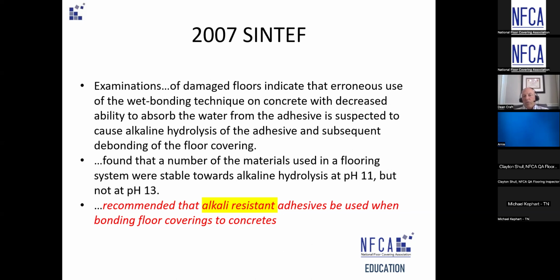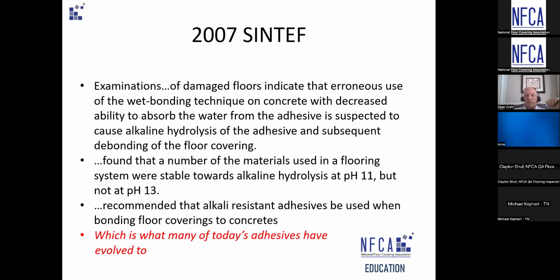But again, the idea that this liquid is soaking into the concrete to bind with the concrete is not really how it works. It's supposed to cure and dry, and that's going to actually help set the material in. But even as far back as 2007, you see how we're coming back again to the pH. They were recommending high alkali resistant adhesives all the way back then, specifically on concrete, because of their research. So this is not new information. In fact, a lot of the adhesive manufacturers on the F710 committee were like, I don't care about pH. So a lot of the glues you're going to come in contact with today are not affected. They'll have a pH limit of 14. They're just saying, hey, whatever, don't care.